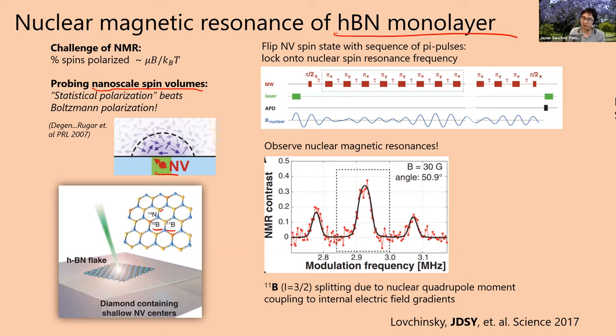What you do is you take your NV spin qubit and we can flip the spin state by applying a pi pulse to it, using a microwave line. By flipping the NV center back and forth, back and forth, it filters out all other magnetic signals except for a signal that's oscillating at a specific frequency, which we can control. So we target the resonance frequency of the nuclear spins that we're trying to sense. We did exactly this, and we were able to observe a nuclear magnetic resonance signal coming from the boron atoms inside of this hBN.